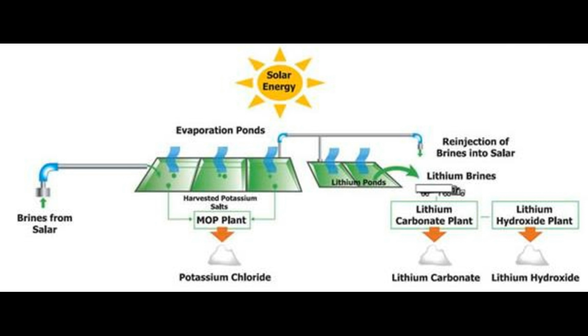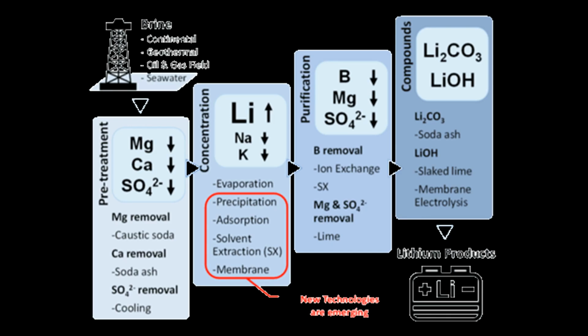Lithium recovery using membrane technologies. Reverse osmosis, RO, and nanofiltration, NF, processes have been studied for pre-concentrating or separating lithium from a lithium-bearing brine. A typical lithium brine usually contains high concentrations, for example 5.0 wt%, of salt ions. The maximum salt concentration that an RO/NF process can reach is linked to the osmotic pressure, as well as the membrane selectivity and the mechanical stability of any associated equipment. Automated chemical softening systems, such as our Brine Refine system, can help membrane treatment systems reliably reach their treatment limits and improve yield. Conventional NF processes cannot efficiently separate lithium without heavy pre-treatment of the brine, such as diluting the brine with a large amount of fresh water.